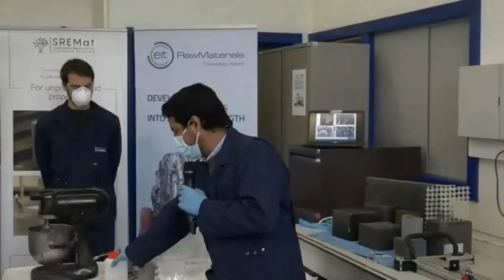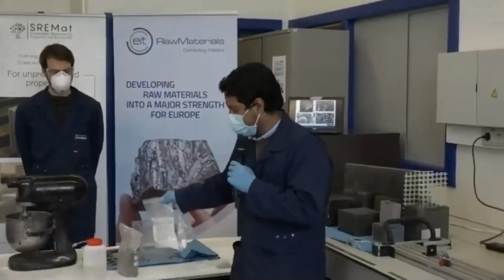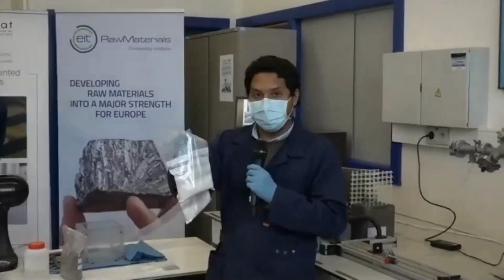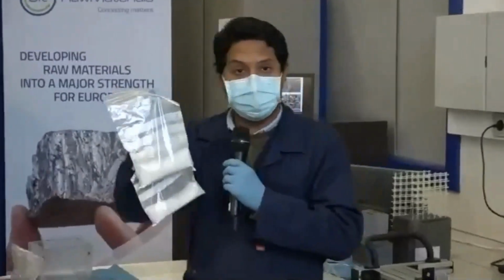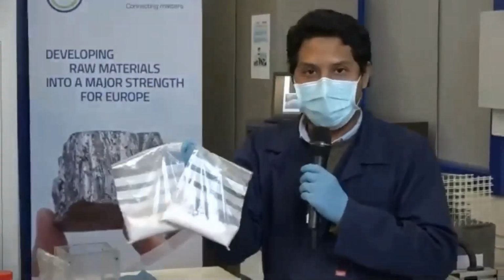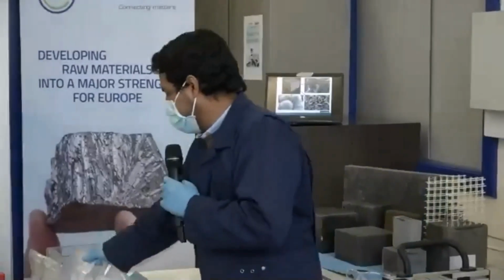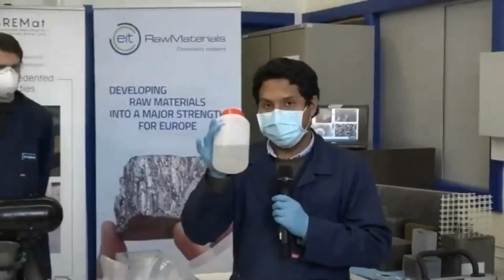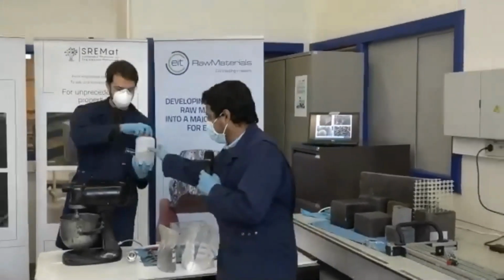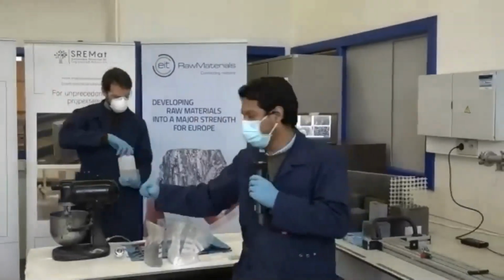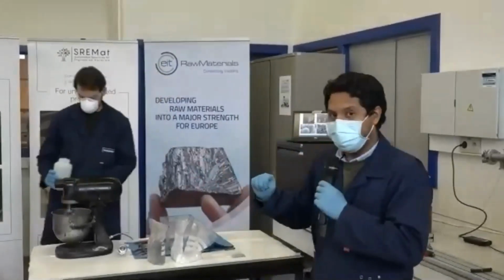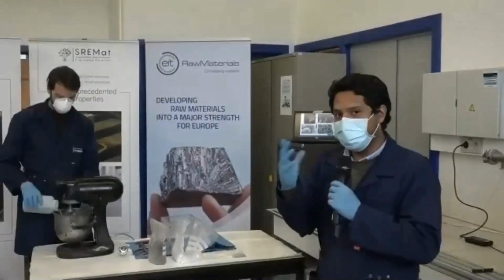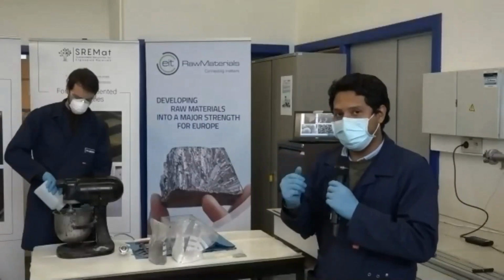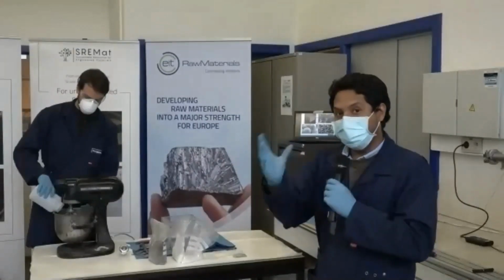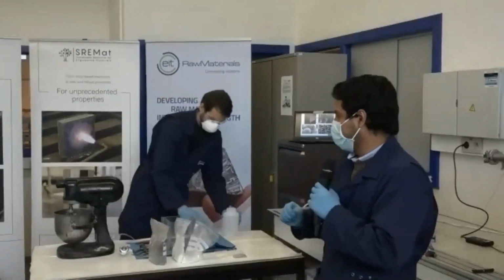And then we will have several other components, as for instance, we have here a little bit of ground granulated blast furnace slag, GGBFS, and also quartz flour. So first of all, we will start making the porous material with the alkaline activator. I will give it to Toby. Toby will put it in the mixer, and with that we will start forming the initial binder, an initial paste that we can actually use as a matrix to create this porous material.